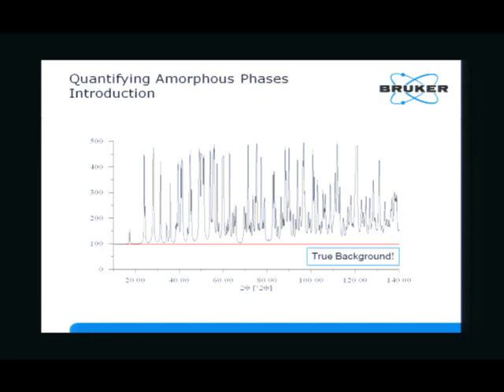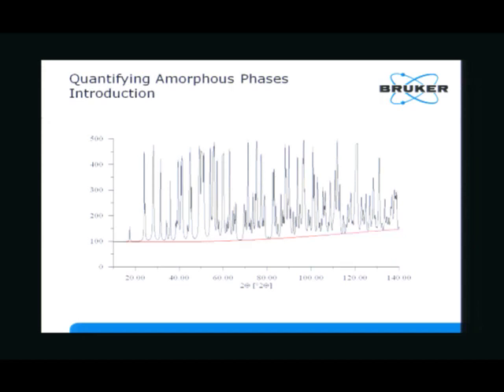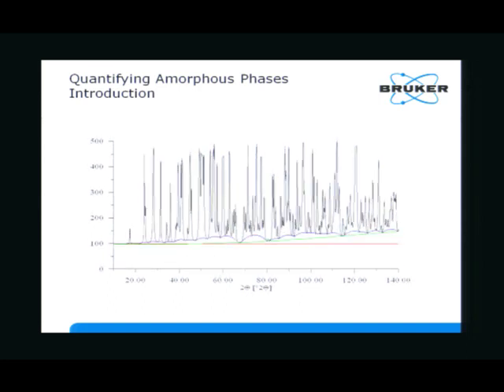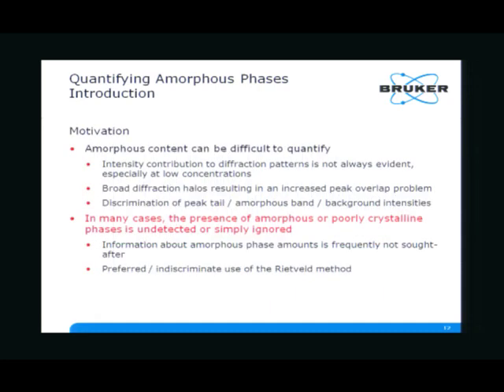Unfortunately real background doesn't look like that, so you can imagine it's even more difficult in real powder patterns. The whole issue is we have an enormous amount of peak intensity in our peak tails — that is apparent background but it's not really background. If you use a background like this you will get very nice temperature factors. This is actually the favorite of spectroscopists — XRF and so on — because they use calibration. An audience of mostly mineralogists or XRF people would have voted for this background, which gives an idea about the problem.